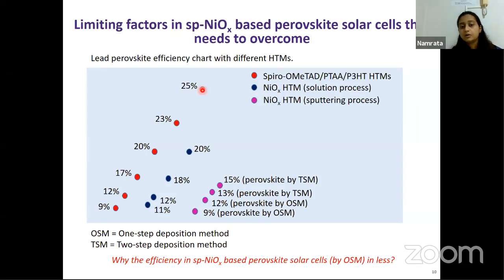Comparing it to nickel oxide, the nickel oxide based cells have relatively lower power conversion efficiency. The blue and the pink dots show the nickel oxide based perovskite solar cells, where the blue dots correspond to solution processed nickel oxide. If we compare the pink and the blue dots, we see that for sputtered nickel oxide the efficiency is further lower. It is 15%, whereas the highest is 25%. This chart is for perovskite solar cells with only lead perovskite.